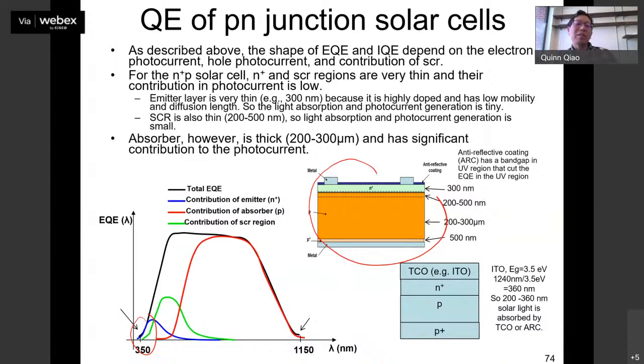One sample, just the surface, the interface samples. You have a very thin layer of this bulk. You don't have a lot of materials there. Then you can study the surface. For other samples, you do the surface passivation. You can control how much defect you have on the surface interface, right? You do the passivation. And then you have thicker films there, you study the bulk, because now you have minimized the impact from the surface or interface, because you passivated that defect, right?